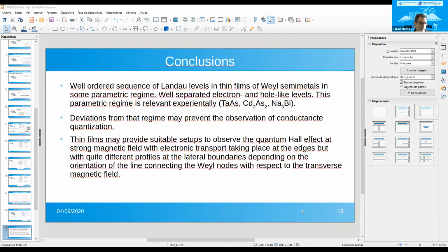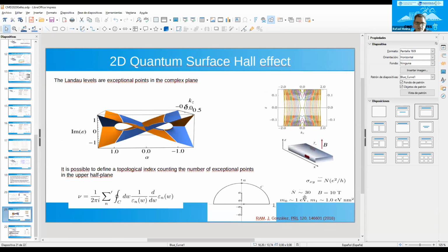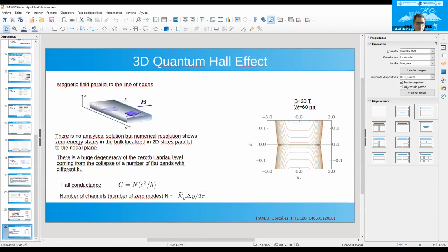Well, in the nodal lines, I can show you. In the Weyl semimetals, you have seen that this is very messy, but in the nodal lines, due to the symmetry of the nodal line that has this whole line of nodes, we can really separate between a 2D quantum surface Hall effect and a 3D quantum surface Hall effect, depending on whether the magnetic field is perpendicular to this nodal line, or in the case of 3D, parallel to the nodal line.